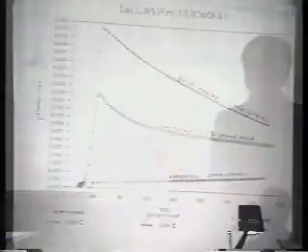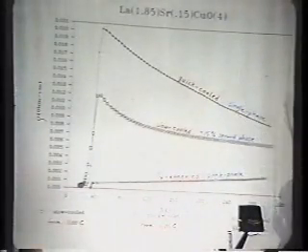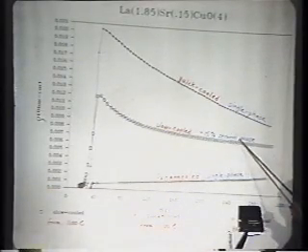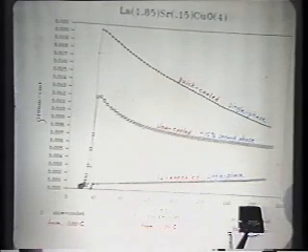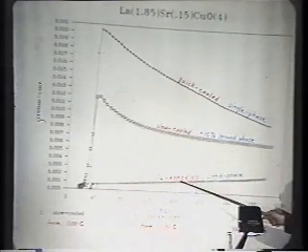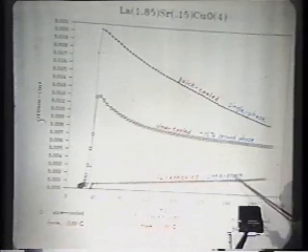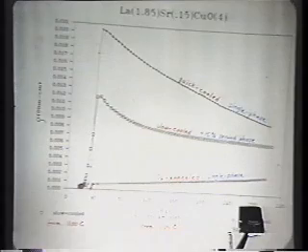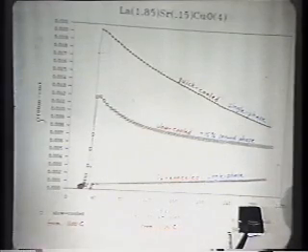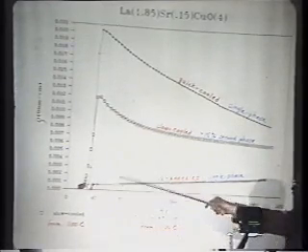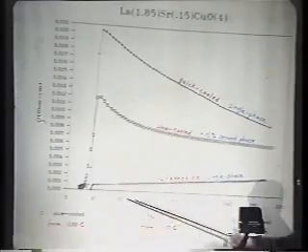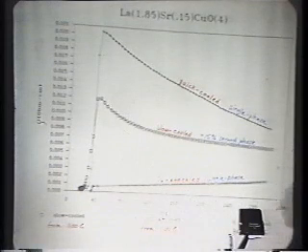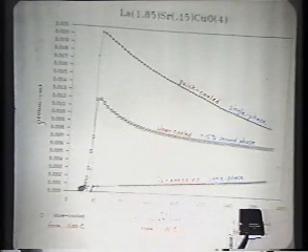The upper curve is for the quick cooled sample, which was found to be single phase by powder diffractometry. The slow cooled sample is 15% some second phase, which we have not completely identified. And the O2 annealed sample is single phase and shows very metallic conductivity, whereas the other two indicate some form of either localized or activated conductivity. The superconducting transition temperature, although you can't see it on this scale, is essentially the same at the midpoint, but the breadth is drastically decreased for the O2 annealed sample, to a width of about 1.5 Kelvin complete.